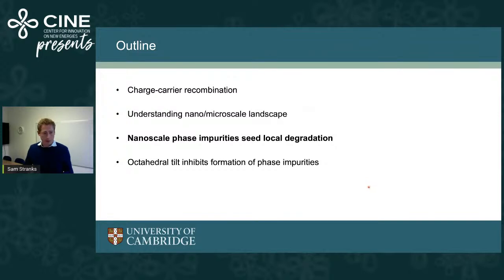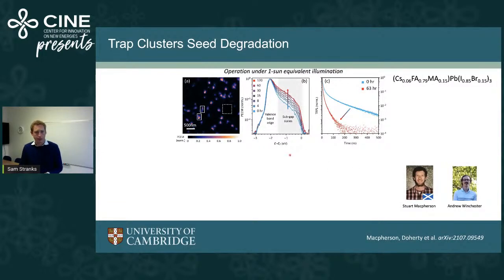Okay, so in the last part, I just want to move into two other topics: how these traps that I talked about just before actually seed local degradation, and how we see degradation over time. This is looking at, again, a photoemission map of a sample, again these triple cation samples, looking at the subgap densities over time under illumination. So here we're essentially operating the solar cell, but with illumination at least. We're looking at how these absorbers change and photodegrade over time. This is over the equivalent of hundreds of hours under one sun equivalent.